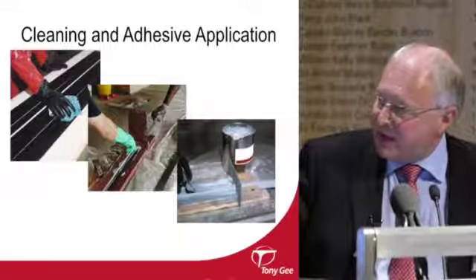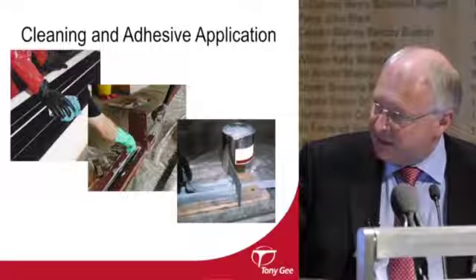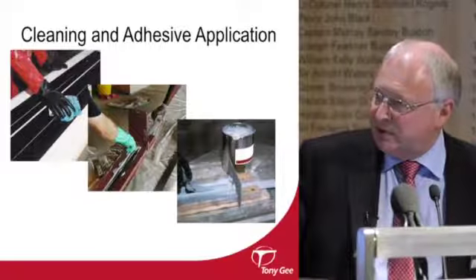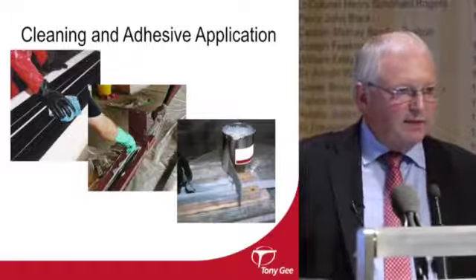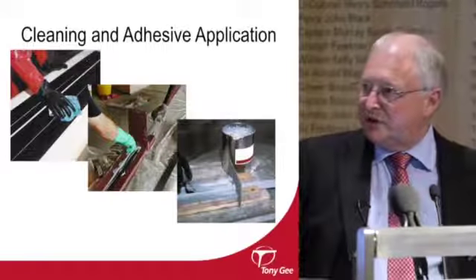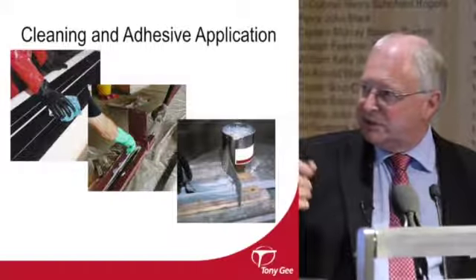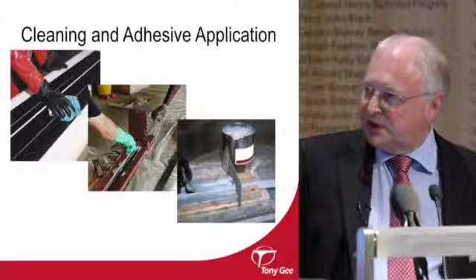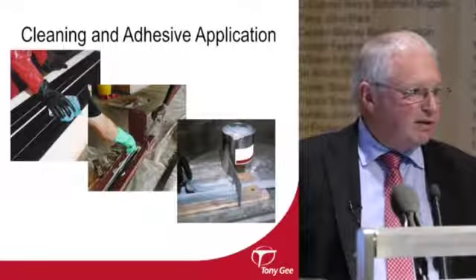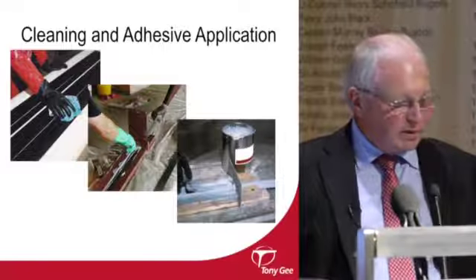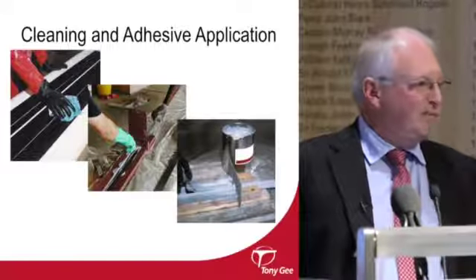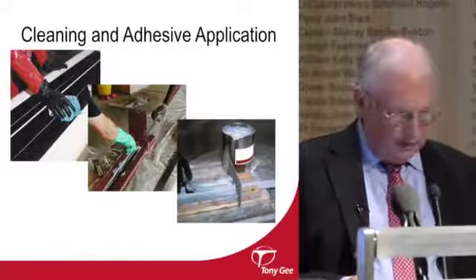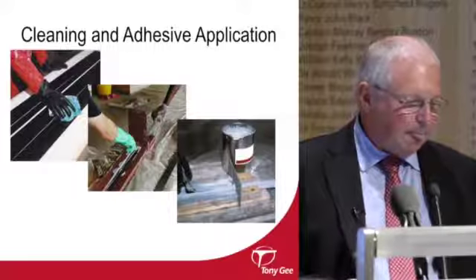This former here actually produces a dome shape on the adhesive, so that when it's eventually applied to the structure and a roller is used to roll the adhesive out towards the edges, no air is entrained in the centre of the strip. So we want a substantially void-free adhesive layer.